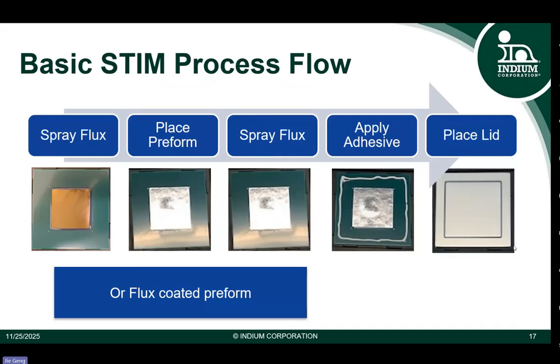We have two different situations. So one is the pure indium without flux. In that case, you have to apply the flux on both surfaces and then do the reflow. For the flux coated preforms, you can just pick and place the preform onto the substrate and then do the reflow. So you don't need to spray the flux on both sides.